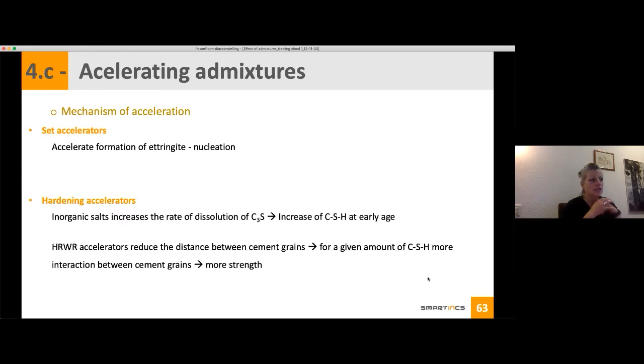If you look at the mechanisms of acceleration, we can accelerate the formation of ettringite or the nucleation of the hydrate. For the hardening accelerator, if you increase the rate of dissolution of your silicates, then you will increase the amount of CSH at early age, and CSH accounts for the compressive strength of your concrete. If you also use a high-range water reducer and superplasticizer, you get water reduction. Water reduction means the distance between two cement grains is smaller than when you have more water. So for the same amount of CSH hydration product, the distance it needs to grow to link two particles is smaller, and then you have an accelerating effect and more strength.